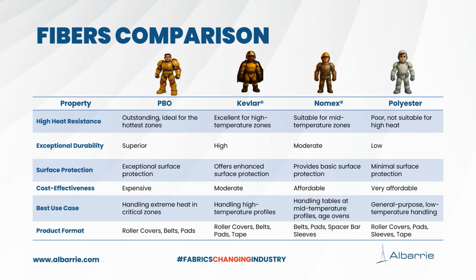By breaking down these properties, we can better understand their strengths, weaknesses, and how to choose the most effective material for your operation. PBO, or polybenzoxazole, I like saying that. PBO fibers are renowned for their exceptional heat resistance, withstanding temperatures up to 1200 degrees Fahrenheit, 650 C. This makes them ideal for use in high temperature areas, such as initial extrusion exit zones, where the aluminum is still extremely hot. PBO also offers superior wear resistance and durability under heavy loads, ensuring longevity in extreme conditions. However, due to its advanced properties, PBO is often the most expensive material, making it best suited for high demand applications.